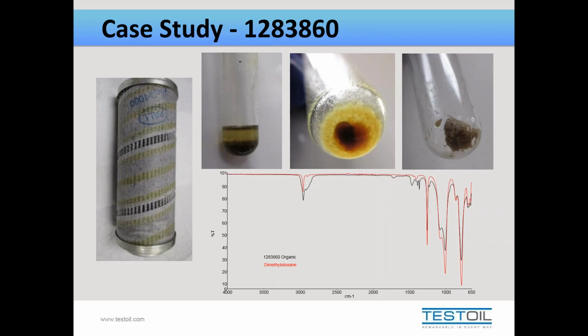So from there, while we were able to identify the extent of the damage, the customer wanted to know, okay, well, why did this damage occur? So then we moved on to material identification analysis, and we started looking at the organic material that we were able to pull out of this machine, or out of the filter media. And you can see that in the middle test tube picture there. And we found ethylene glycol, which is expected since the fluid in use was an ethylene glycol-based hydraulic fluid.